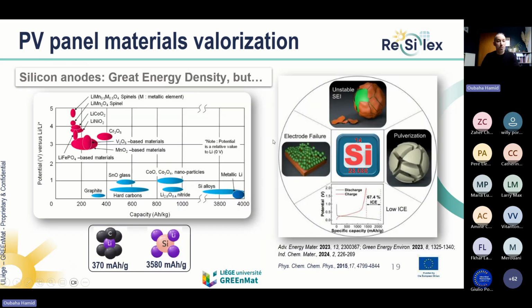Why is silicon interesting in lithium-ion battery applications? Actually, the reaction between lithium and silicon is known since the 70s, to form lithium silicon alloys. But if we look at this reaction, silicon reacting with lithium can lead to a lithiated silicon which has 10 times the capacity of the graphite used. It takes 1 silicon to store 4 lithium ions, while in the case of graphite you need 6 carbon atoms to store just one lithium. Also, silicon has a relatively low working voltage, leading to high energy density.